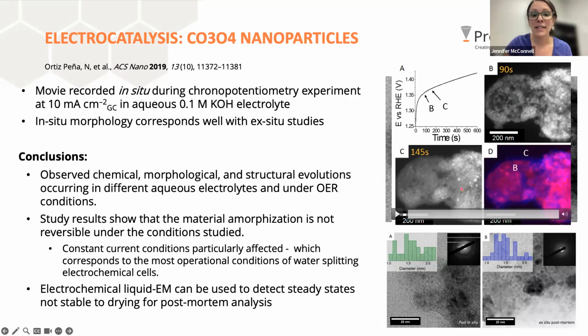There was some significant amorphization that occurred, and they noticed that it's not reversible to get it back to a crystalline state. One other thing they noticed was when they analyzed the size of the particles at the end of the in situ experiment, while it was still in liquid, they got certain results here.